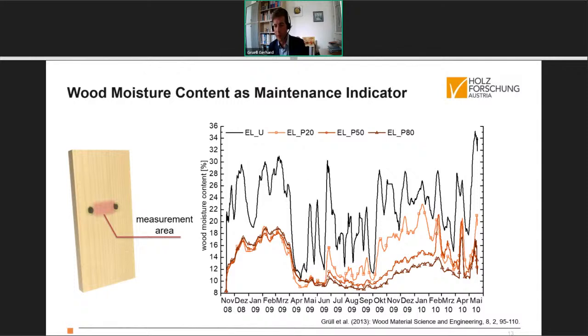And then here in June 2009, it starts, the system P20 with 20 microns starts fluctuating more. And in visual inspection, we found out that this was with the occurrence of cracks in the coated surface at the same time. So it fluctuated more, and here the next coating systems with 50 microns started fluctuating more, whereas the system with the highest film thickness had the highest durability.